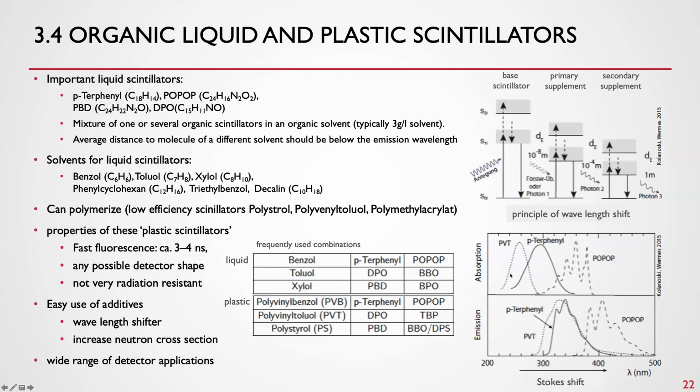So between absorption and emission of the mixture of these compound plastic scintillators, we can go up and down several times, and at the end we will land at an emitted scintillator light at the longest wavelength. The decay time of these plastic scintillators, despite the fact that the reactions here are fairly complicated, is 3 to 4 nanoseconds.